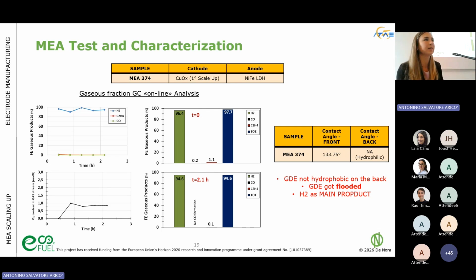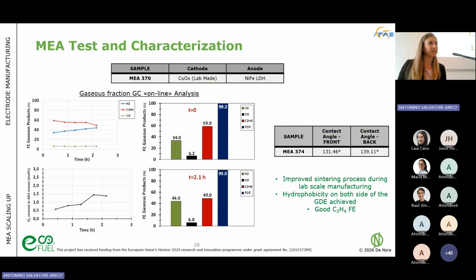So we saw that the key parameter that we need to modify is the hydrophobicity of the GDE, not only on the front side, but also on the back side. And so in the lab, we tried to adjust some factors, some processes, working on the sintering, so changing the temperature and the time of the sintering. In this case, you clearly see from the contact angle that the backside is hydrophobic. And if we look at the GC analysis, we do have nice production of ethylene, even after 2 hours of test.